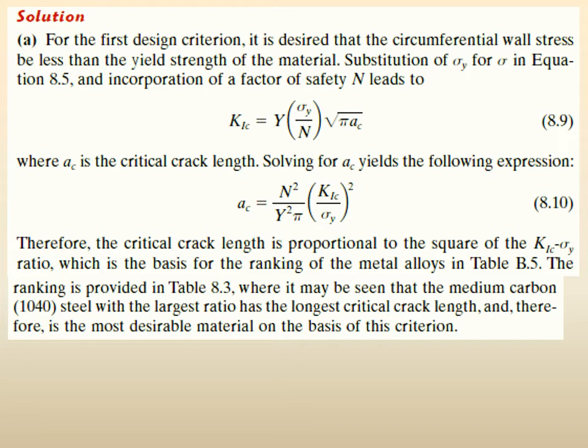And therefore, there is only this equation. There is no other equation. There is one equation, remember, the Griffith crack equation. But in the Griffith crack equation, we have the material property called specific surface energy. Here in the table that we showed you last time, we have the K1C values, fracture toughness values. So based on fracture toughness values, there is only this equation. The equation is K1 is equal to Y sigma root pi A. Remember, K1 is equal to Y sigma root pi A. Now K1 will become K1C when the sigma is the critical sigma and the A is the critical crack size, isn't it?